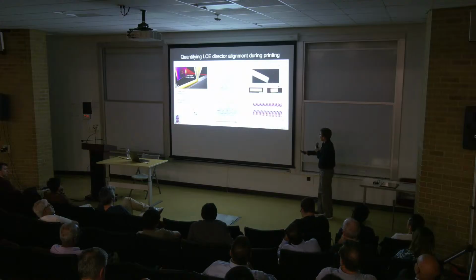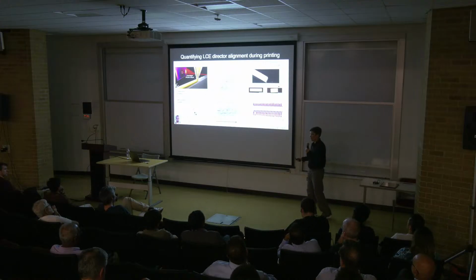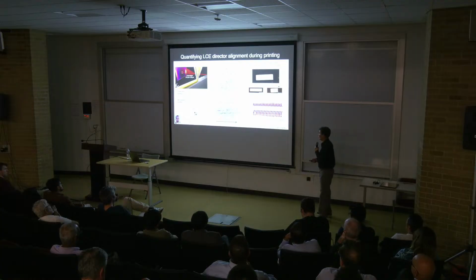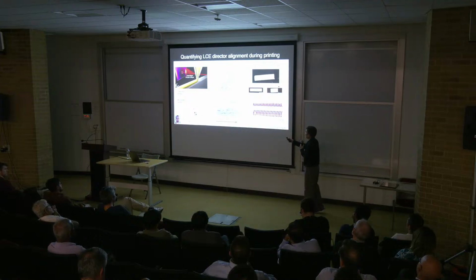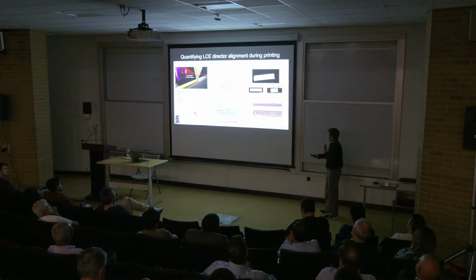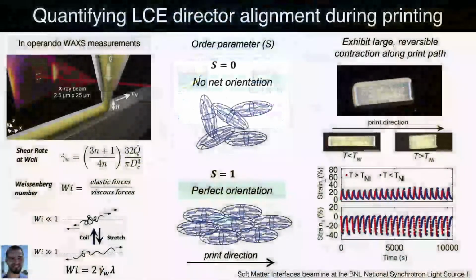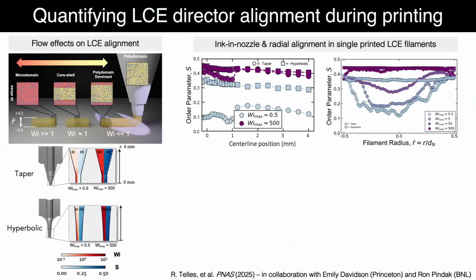Now, in the perfect world, we would love to have an orientation and order parameter of 1. It's really not possible with these main chain liquid crystal elastomers, but in the isotropic state above TNI, essentially there would be no order, okay? So we're printing, remember, in the nematic state, so we should see S greater than 0, but we won't see S approaching 1. So what does it look like? First of all, we did 2 different nozzle designs, a tapered nozzle design and a hyperbolic nozzle design. The taper nozzle is pretty much what we use normally in our laboratory. But because we can 3D print any nozzle, like our rotation nozzle is a good example, we created this hyperbolic design which provided an extra extensional component to the flow, not just shear flow.